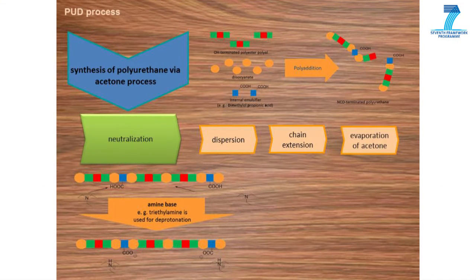OH groups react with diisocyanate to incorporate the internal emulsifier into the polyurethane backbone. COOH groups are used as ionizable groups which will stabilize the final aqueous dispersion. Synthesis via acetone process.